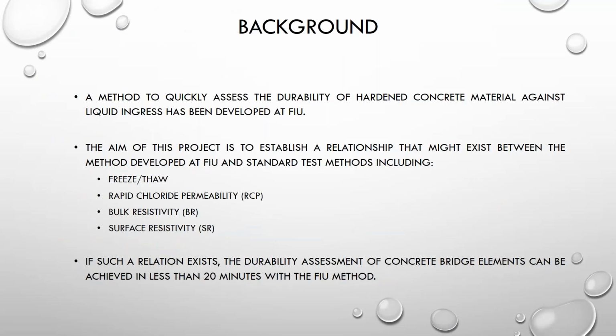A method to quickly assess the durability of hardened concrete material against liquid ingress has been developed at FIU. The aim of this project is to establish a relationship that might exist between the method developed at FIU and the standard test methods, including freeze-thaw, rapid chloride permeability, bulk resistivity, and surface resistivity. If such relation exists, the durability assessment of concrete bridge elements can be achieved in less than 20 minutes with the FIU method.